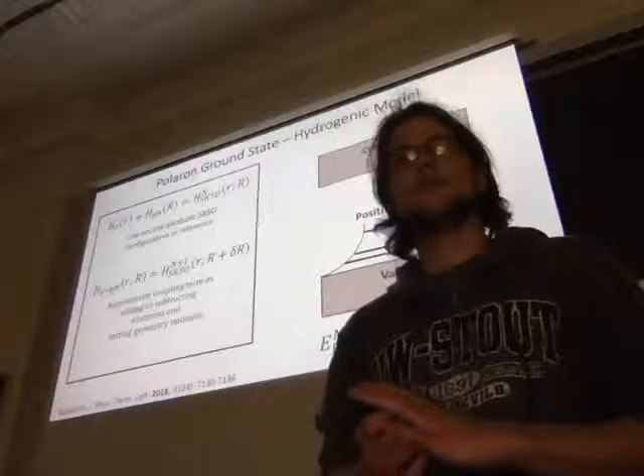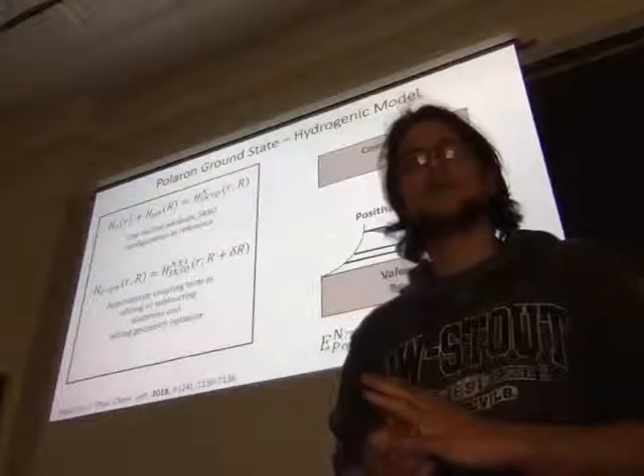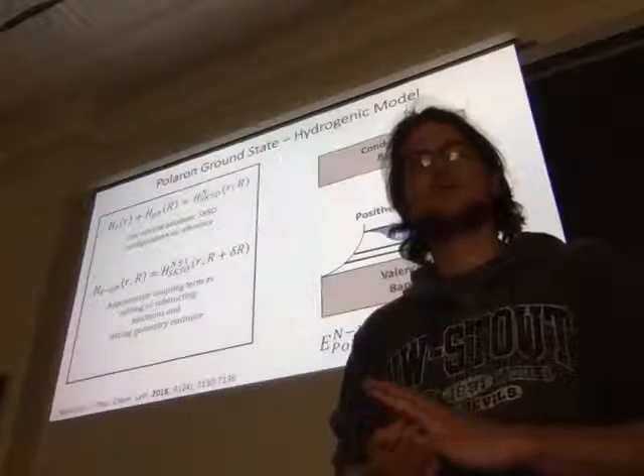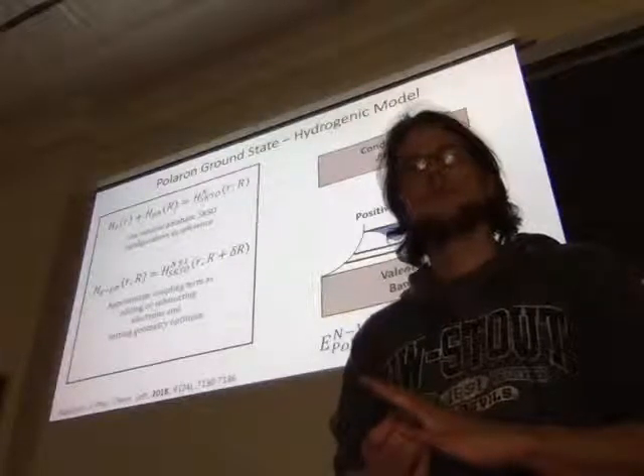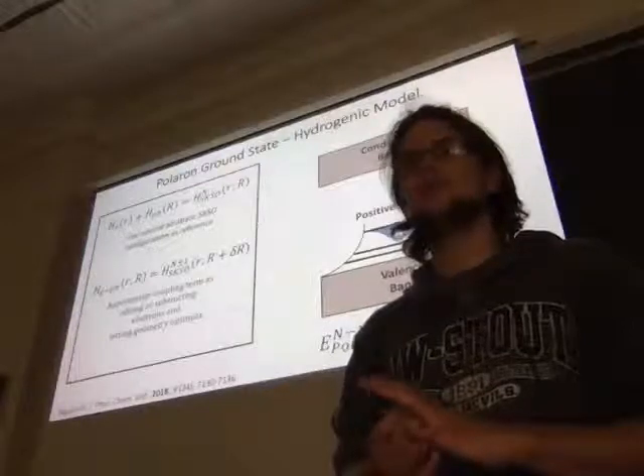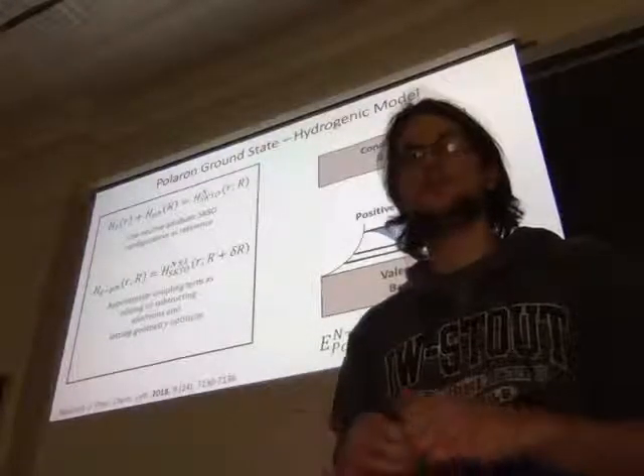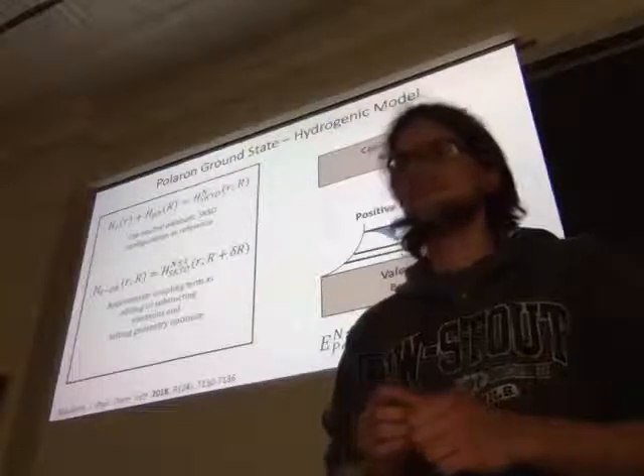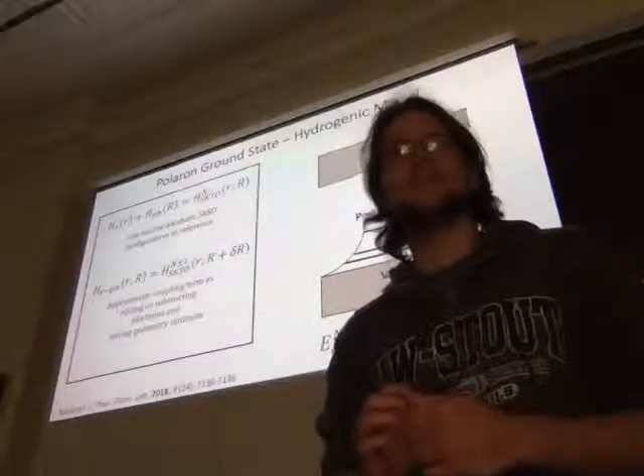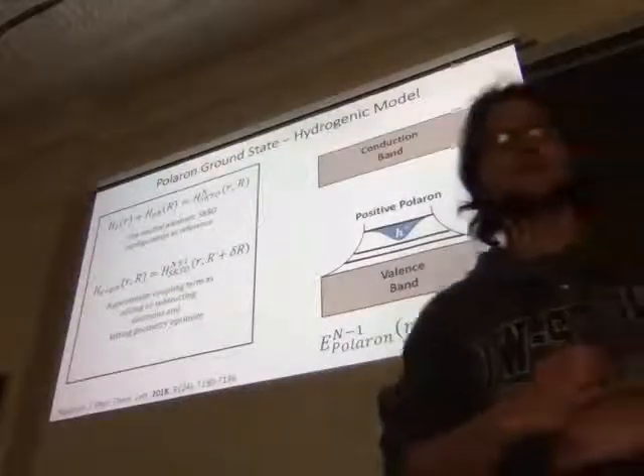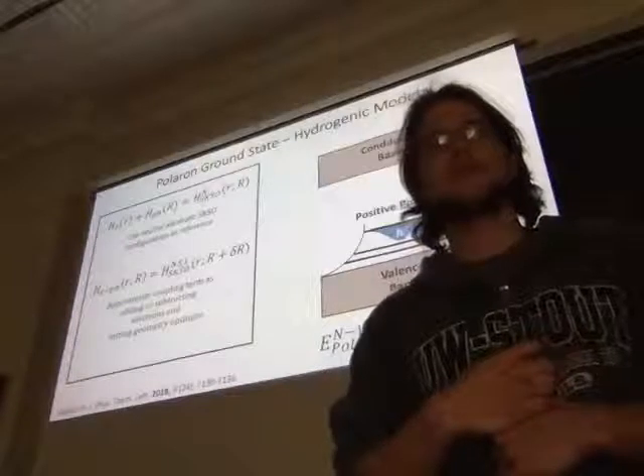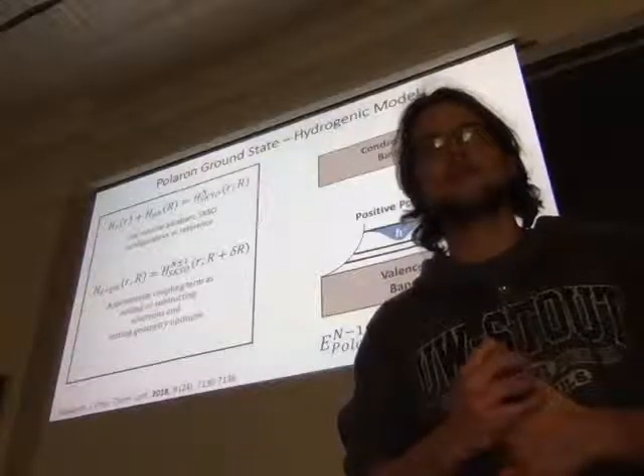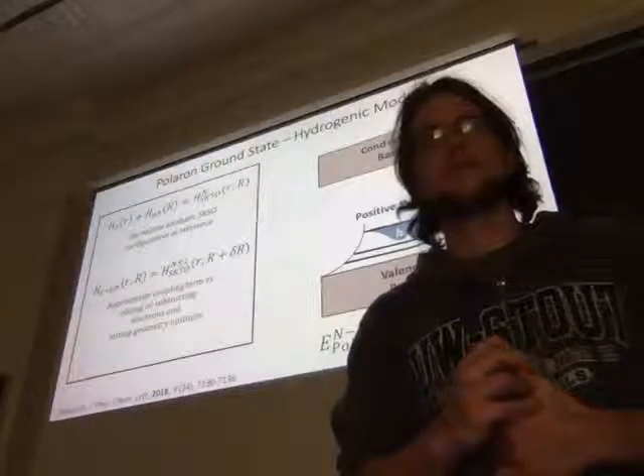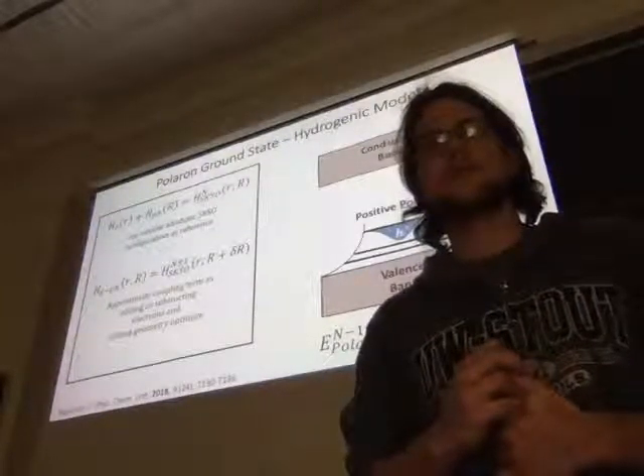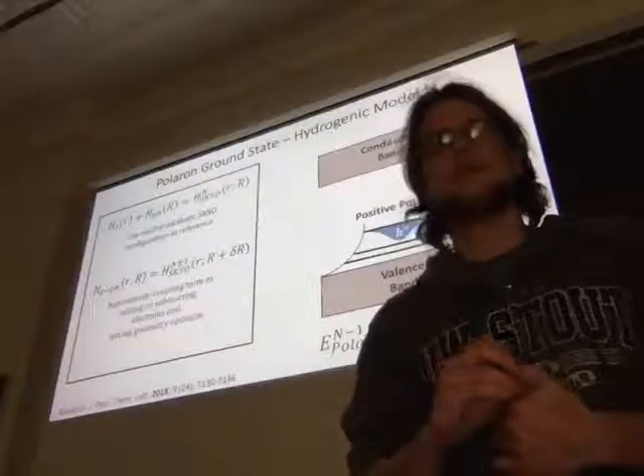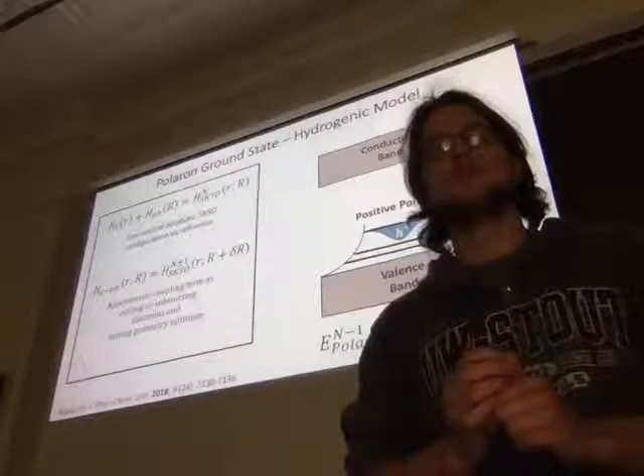I'm thinking about whether, when you go to a small system, because of the quantum confinement, the polarons would be smaller and you might not want strong ones. Yes, these would be small polarons compared to what would be seen experimentally. But I guess it's the best we can do at the moment. I'm not talking about the size of the system, because it's 1,000 atoms, more than 2,000 electrons, I think that's enough for us to do it. But I'm thinking about when you go to a smaller system, a nanocrystal, because of the confining effect, the polaron state can be more localized than in the bulk.